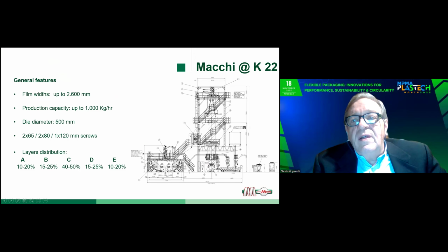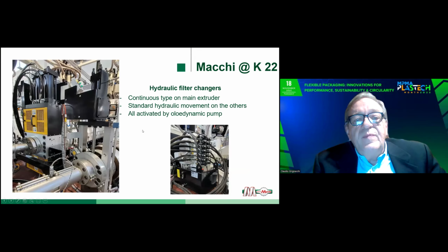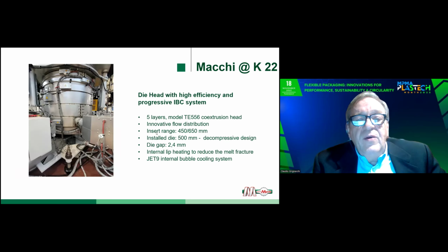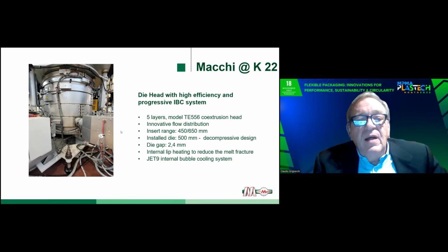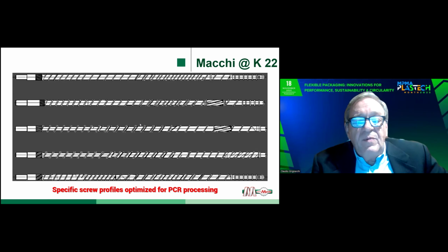Throughout K22, we were running constantly 800 kg per hour of film with an overall total percentage of PCR up to 35%. This was achieved using hydraulic filter changers to change the screens without stopping the line, a newly designed die head able to process and homogenize the PCR perfectly, and a range of screw profiles optimized for processing PCR resins.